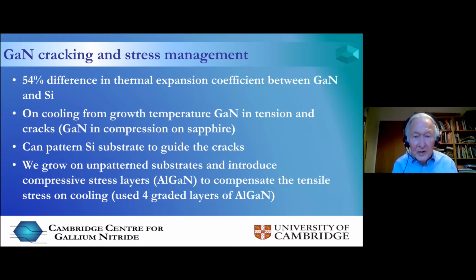And so what we did, we introduced deliberately compressive stress layers to compensate the tensile stress on cooling. And this was really quite sophisticated stress engineering at the atomic level in these materials. We formed 4 graded layers of aluminium gallium nitride. And the next slide shows schematically what's being done.